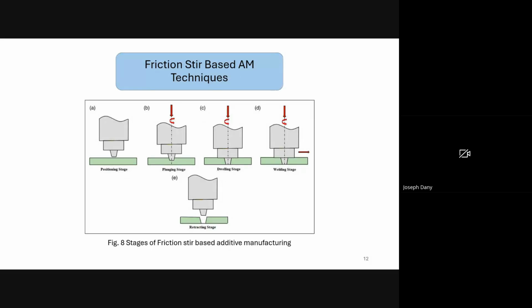This entire stirring process leads to dynamic recrystallization, which produces fine equiaxed grains and results in excellent mechanical properties in the weld joint. Finally, the retracting stage. Once the weld reaches the end of the joint, the tool is lifted out. This leaves a small exit hole, but in practice, welders often extend the weld length slightly or use refilling techniques to avoid this hole.